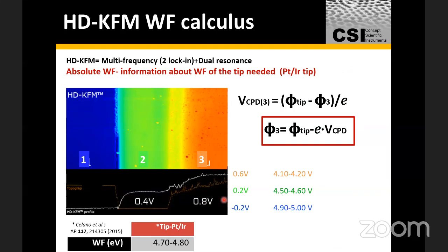So here's some typical data now, where we are able to translate the measurements we make into equivalent work functions. As you will see, this semiconductor surface is patterned in such a way that you get preferential work functions at the different designed regions of the surface. So you can see that you get various work functions all the way from minus 0.2 to about plus 0.6.